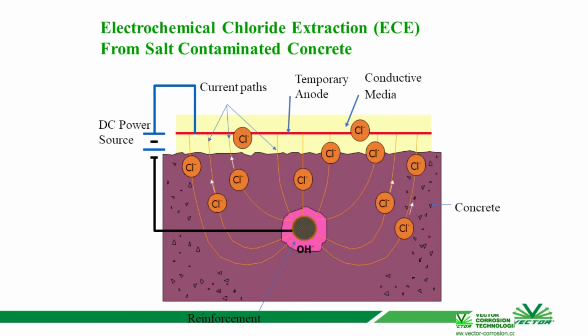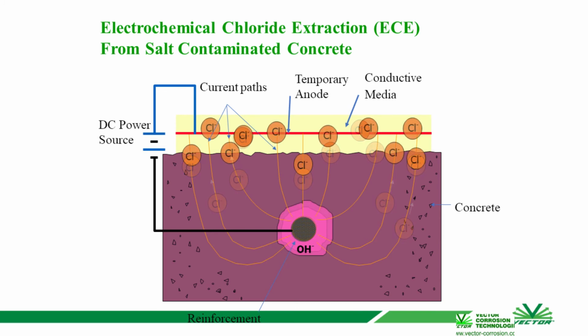What you do is you'll set up a temporary anode on the outside of the structure. We usually use a welded wire mesh, and then you're blowing in some type of conductive media or a temporary electrolyte to help the current go from your structure to your temporary anode on the outside. You'll hook up a direct DC power source, so your positive is going to go to your anode and your negative to your reinforcing steel.